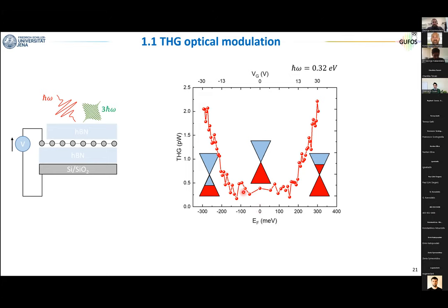And now you see this curve that I like very much, it's very beautiful in my opinion, where we can see the enhancement in the third harmonic. There is no pump here, this is only gate tunability, but now the enhancement can occur symmetrically in the p-doped and n-doped region. I think this is the nonlinear analogue of the ambipolar field effect transistor, ambipolar field effect behavior, that tells us that there is a full analogy between electrons and holes within the Dirac cone. And this is what we can observe here for the first time.